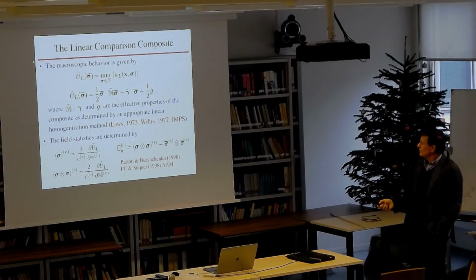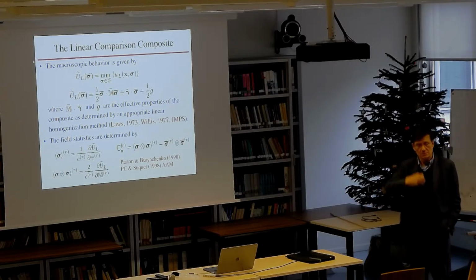On the other hand, for the field statistics, the formula that I gave you earlier simplifies, because the material is quadratic, well, not quadratic, corresponds to linear behavior, and then you can get the first moments and the second moments using these relations that go back a while, and you therefore can also get information on the covariance tensor of the fluctuations. You introduce this linear comparison material that has the same microstructure as the nonlinear, the same class of microstructures as the nonlinear, because remember, we're doing this for a random system.